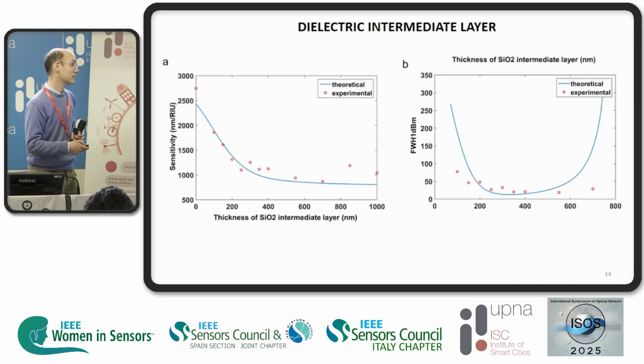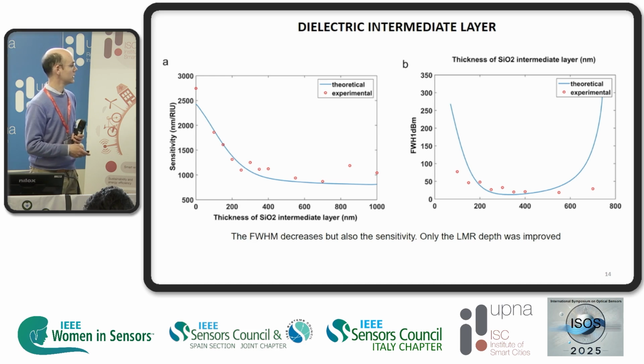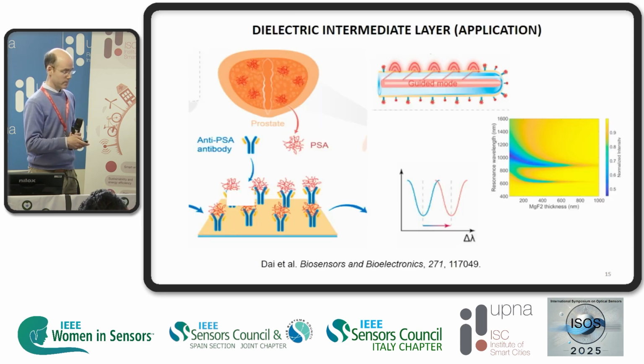It is interesting to observe that the good point is the visibility, so the full width at half maximum could be improved, but the sensitivity also decreases. So the bad thing in this work is that the full width at half maximum decreases, but also the sensitivity, so in the end the figure of merit is quite similar. I must point out that this non-improvement is due to the quality of the thin film. If we improve the quality of the thin film, we could improve the figure of merit.